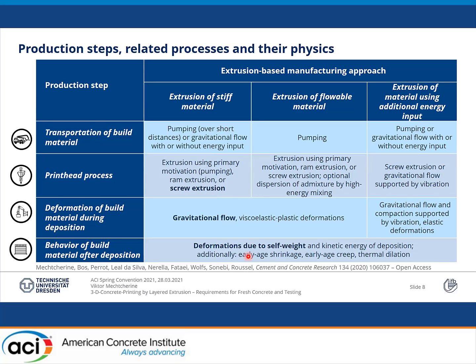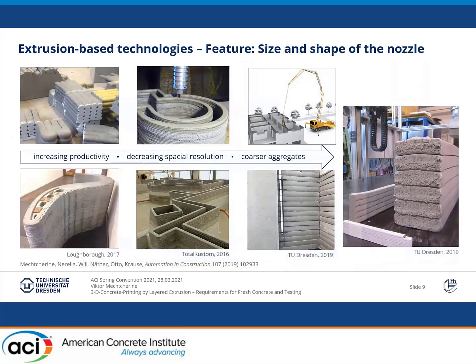I will not address pumping today — sorry Peter, the speaker of the previous session — but I appreciate your reference to our work. Before going into particular processes, let me emphasize another important parameter: nozzle geometry. On one hand, it affects massively the material flow and accordingly the requirements for rheological properties. On the other hand, larger nozzles enable use of mixtures with coarser aggregates, which not only yield different rheological behavior but also need different equipment for testing in comparison to fine mortars.